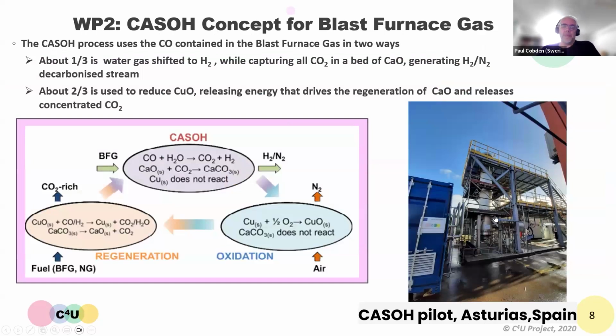So the second technology is called CASOH. It uses two materials, one being calcium oxide, calcium carbonate, the other being copper. There's a three-step cycle for this process. You see the pilot plant built in Asturias, Spain, at the ArcelorMittal plant there. The special thing in this project is that if you need to decarbonize through calcium carbonate, you have to bring in a lot of heat into a process. And it just so happens that the reduction of copper oxide to copper using hydrogen is a very exothermic process. And this can produce heat right in the center of your reactor to decarbonize or to calcine calcium carbonate in order to make CO2 again.